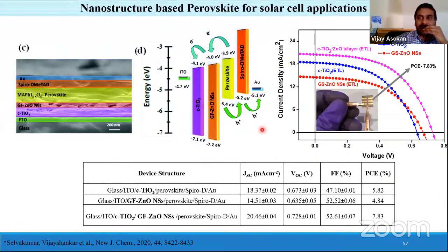So this is the efficiency diagram which we pointed out, and we calculated with compact titanium dioxide, then with zinc oxide nanostructures, then with a bilayer combining titanium dioxide and zinc oxide together within the device. We calculated the efficiencies, and using the bilayer, the efficiency is improved. Such a graph is shown here with the IV diagram. So these are the things we have worked on so far towards the electron transport layer and the hole transport layer, and also over the perovskite materials. It's broad research work carried out with our PhD research student who recently submitted his PhD thesis.